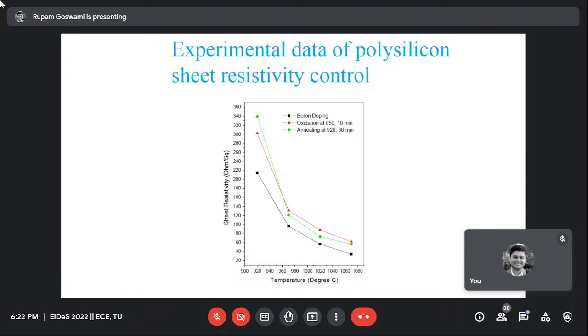Okay, so the whole work in these two or three slides is about how the technology comes in between in the design. When we want a resistor of a particular value having a particular dimension, there is a technology involved there, how to control the sheet resistivity. And this work shows that we can control the sheet resistivity of the active layer by the doping process, by annealing, and so on. This is quite clear here: if we do this temperature annealing process, then sheet resistivity comes down. And this is very clear over here in all the cases.